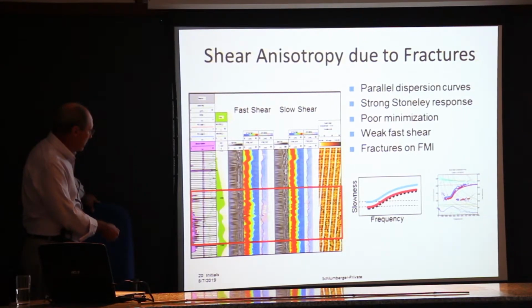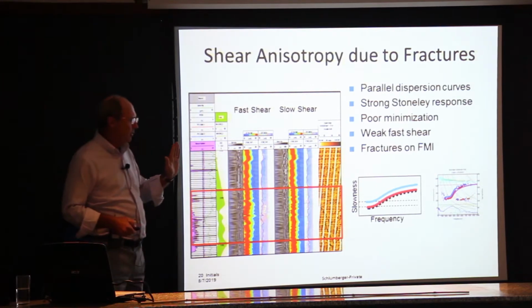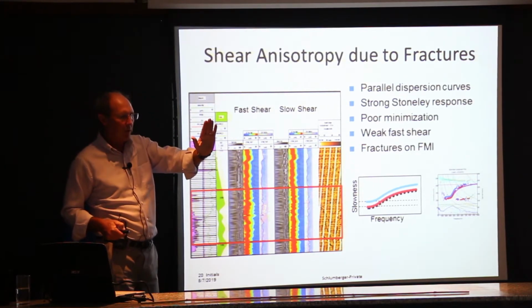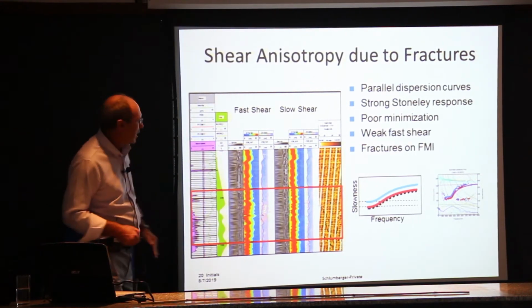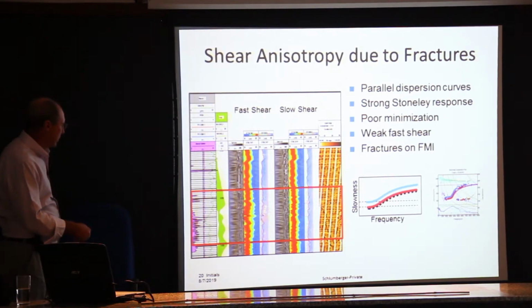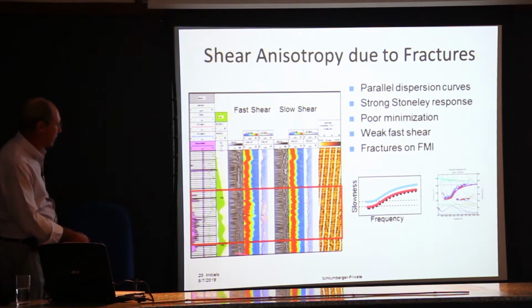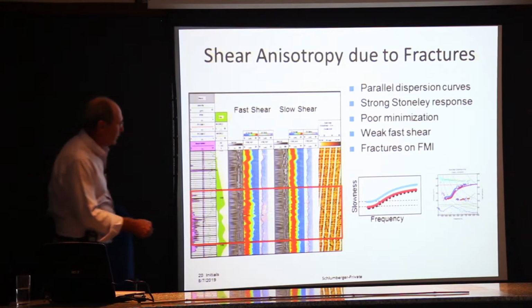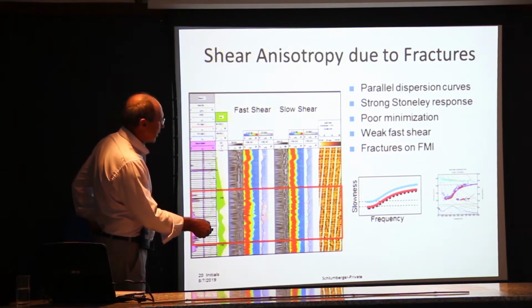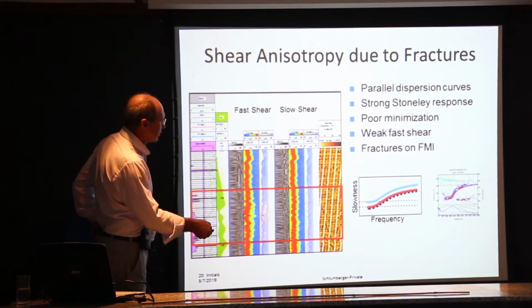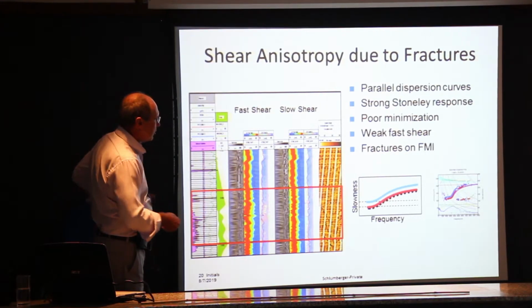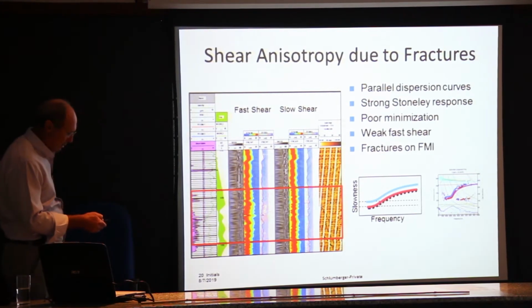And what you have here is an indication of fractures seen by the Stoneley wave based on reflections. When the Stoneley wave sees a fracture, it pumps the water into the fracture and also sends a reflection back. So we can look at both the slowdown in the Stoneley wave and the reflections as an indication of fractures. So you can see, we see these fractures right here. This is a cartoon of the data. This is the actual data. Red is the fast shear, blue is the slow shear. You can see that this parallel effect.